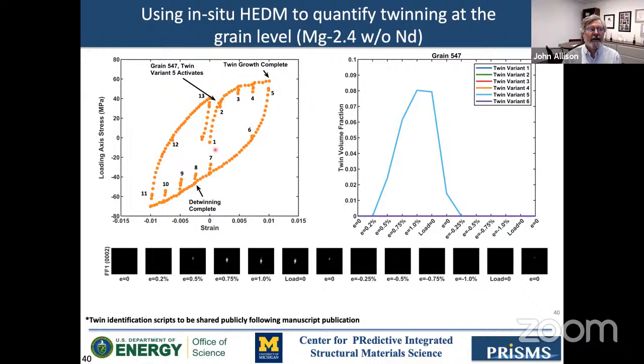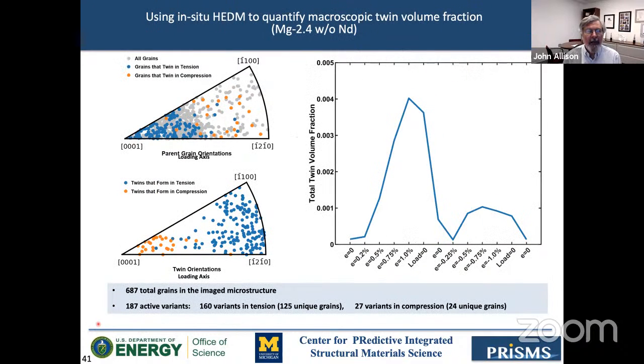And so here's a particular macroscopic stress strain response. And he said, well, okay, here this grain 547 starts to twin. Twinning is completed, then twinning is detwinned in that particular grain. And he can also determine the variants in each of these. And this is sort of a map. So neodymium has what's called this rare earth texture. So it's a weaker texture. So we actually don't see nearly as high a twin volume fraction in these alloys because of its weaker texture. And so these alloys tend to be more formable.